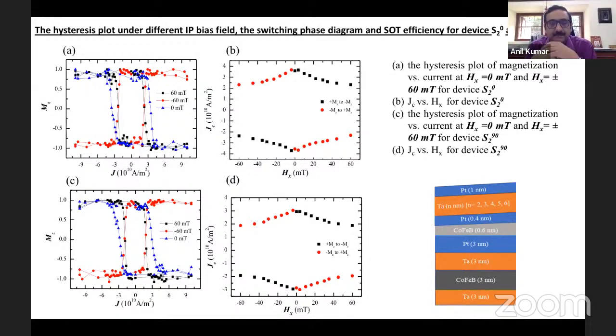So does the magnitude of this gradient matter? It matters, because if there is no gradient, there's no switching without magnetic field. And by the gradient, we can also find out how much the magnetization is tilting with an accuracy of 0.3 degree. If the magnetization is perpendicular, and if it is away by 0.3 degree or more, we can even measure by these techniques.